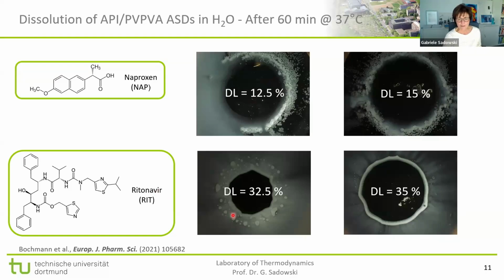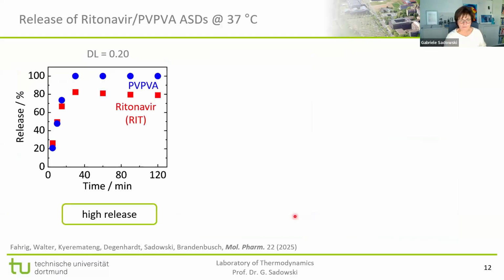And the same is for ritonavir, but here what was observed in literature is that we don't have a formation of a crystalline shell, but of an amorphous shell. And this again depends on drug load. So the higher the drug load, the worse it is. But what you can really see is that this is the inner of the ASD. You have a shell formed, and in the liquid we also have droplets formed. So there's obviously also phase separation in the surrounding liquid. So this looks like a thermodynamic problem, and this is where we then start to look at it.